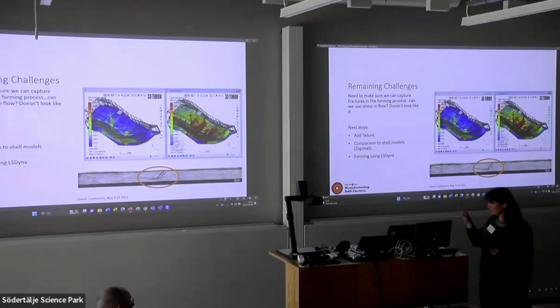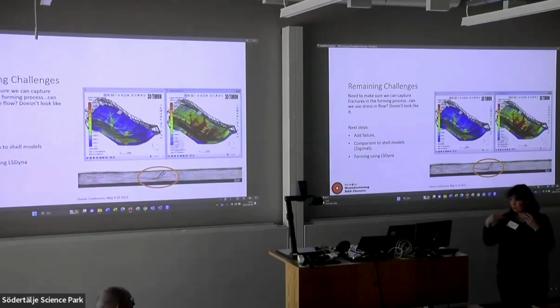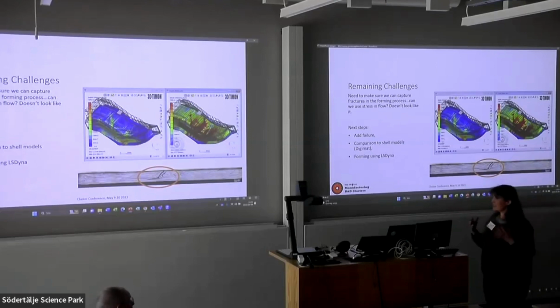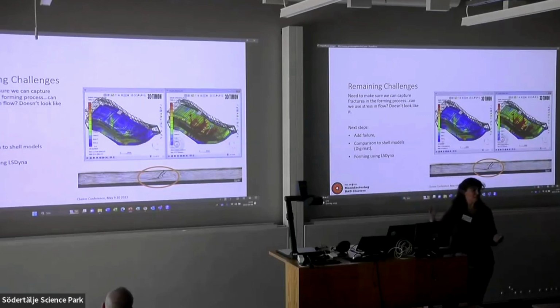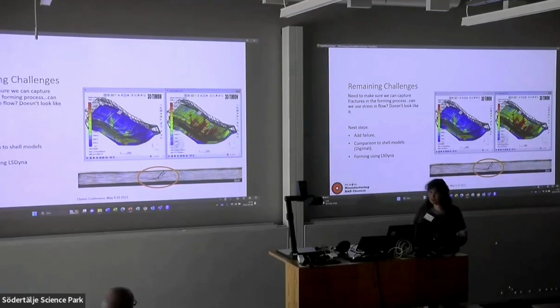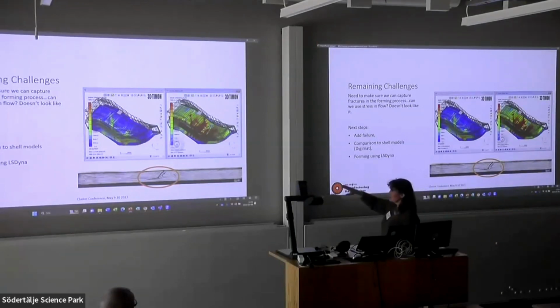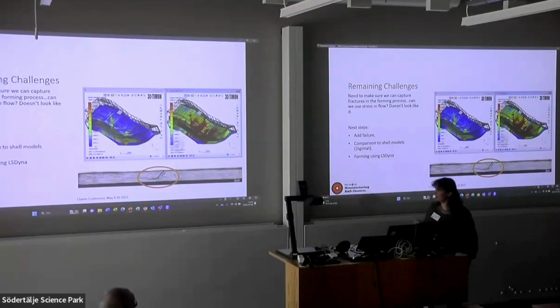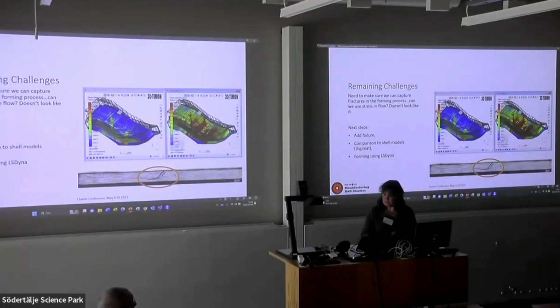The advantage of using this model is that it's a micromechanical model, so you can test a few different fiber volume fraction options. We want to have the least amount of fibers as possible because then it flows really nicely and you have much fewer issues. But you want to find out where that boundary is. By using these models, at least we can get a first stage check. Yes, it looks like 40% is going to be enough, or 20% is going to be enough, or what the issues are. And then you can go on to using Digimat and get a better result from it. And like I said, we would like to look at using LS Dyna for forming. So